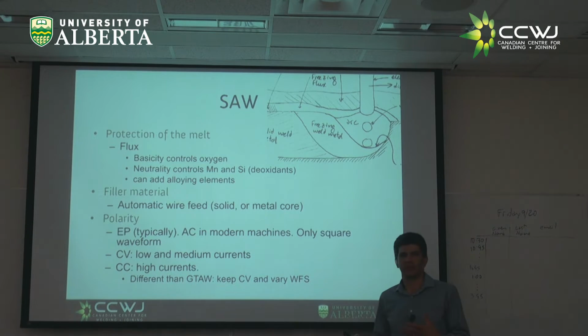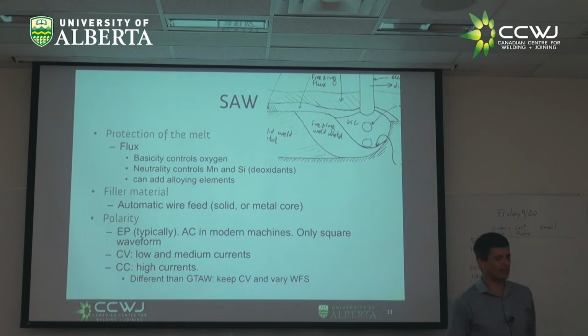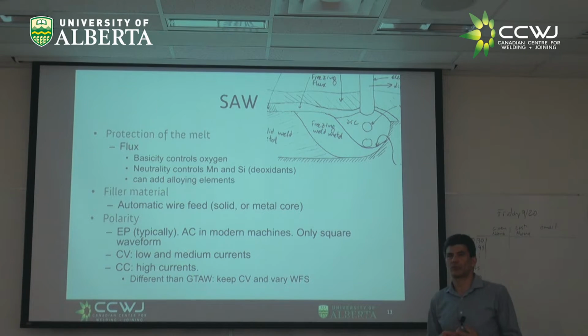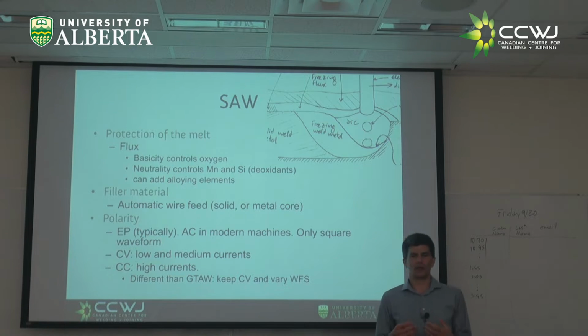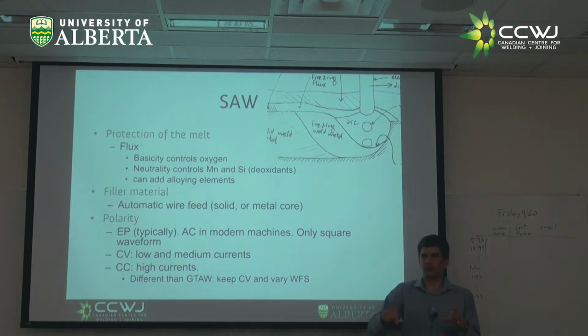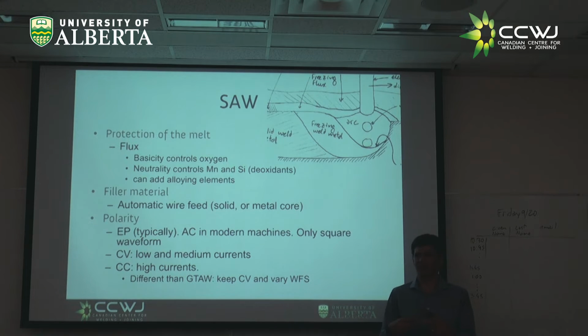You can add alloying elements. For example, imagine you have a steel plate, but you want to make an overlay that is very high in chromium and carbon, such that it gets chromium carbides and is very wear resistant. You can do it with submerged arc welding because in addition to putting just the ceramic powders, you can put, for example, before the ceramic powders, all these high chromium and high carbon powders that will be molten and will give you this super wear-resistant alloy, right? You can play so many games, as long as you know what you're doing.